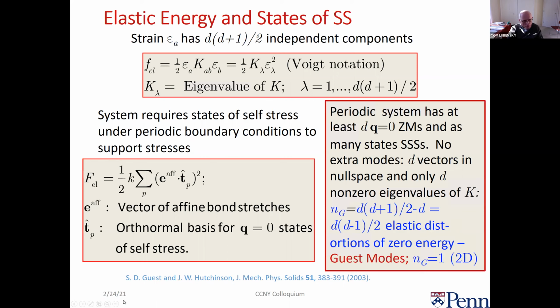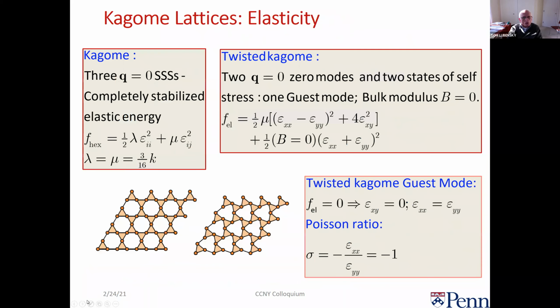So let's see here. In the kagome lattice, I have three zero modes, because I have the three different directions of the straight lines. And therefore I have three eigenvalues, and I have a stable elastic energy exactly here. In the twisted kagome, I only have two zero modes instead of three, which means I only have two states of self-stress, and one of the eigenvalues has to be zero, and it turns out to be the bulk modulus that is zero.